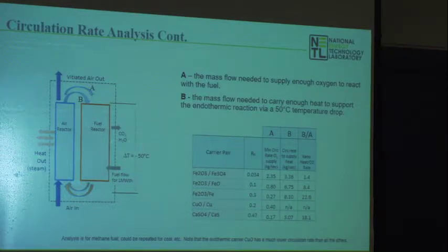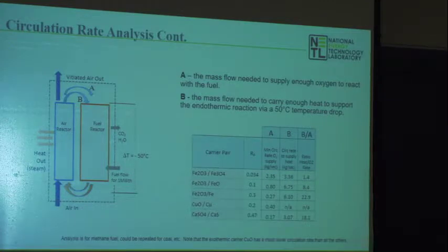So then I get down here to the calcium sulfate. This thing, remember, has lots and lots of oxygen capacity. All right? Half the stuff coming around with that carrier is oxygen, and looky, I just barely need to supply any in that circulation to burn up that fuel. So it all makes sense. Depending on how much oxygen I get off the carrier, I can reduce the amount of circulation. That was if I'm just supplying oxygen.